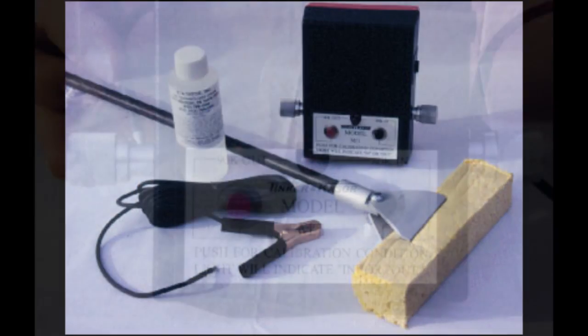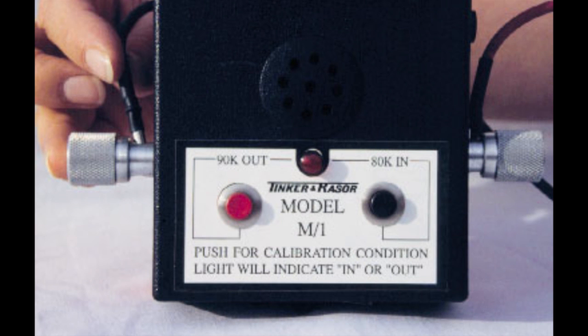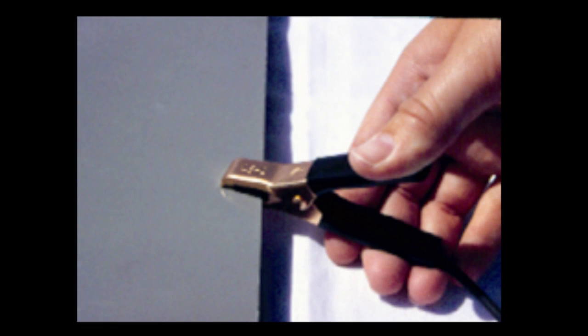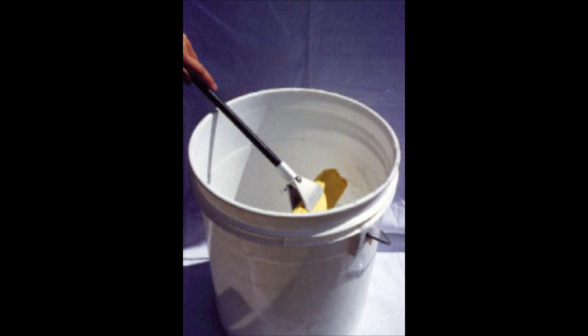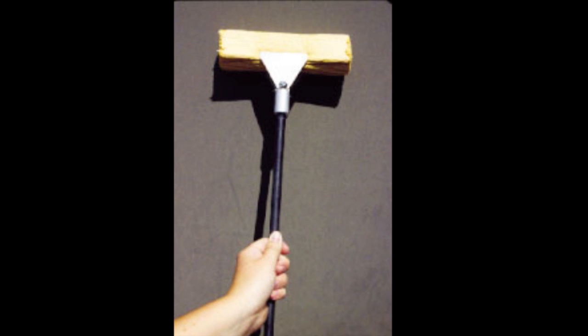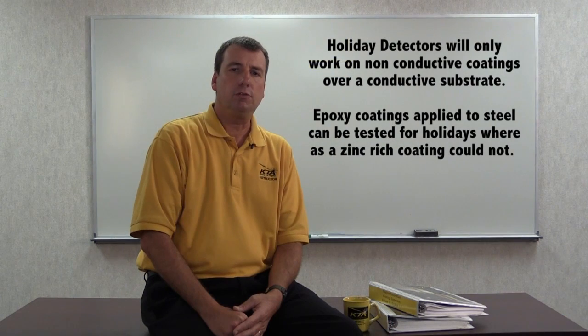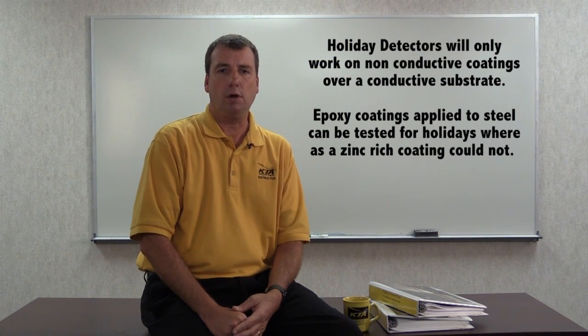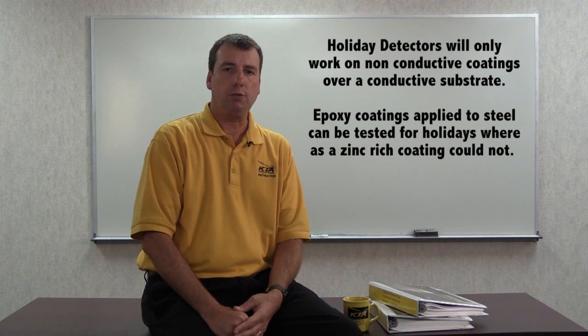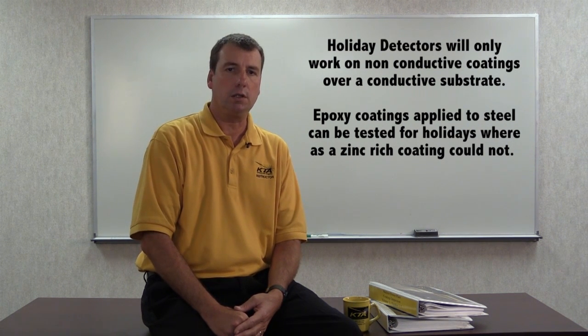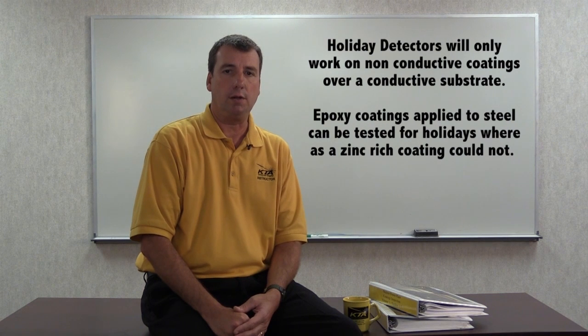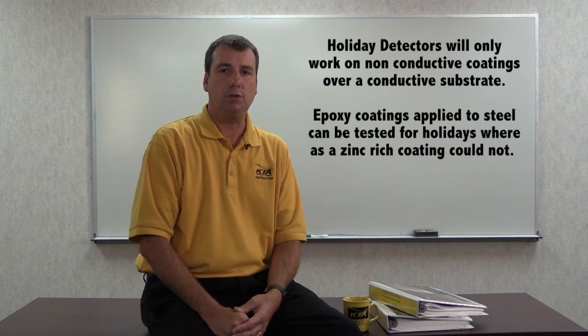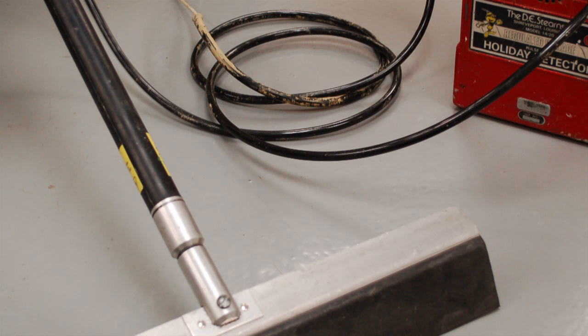Holiday detectors operate by applying a current to the surface of a non-conductive coating and grounding to the substrate. The current passes through the pinholes or misses, completing an electrical circuit, designating the presence of a flaw. Since these detectors will only work on non-conductive coatings applied to a conductive substrate, epoxy coatings applied to steel can be tested for holidays, whereas a zinc-rich coating applied to the same steel could not, since zinc is a conductive metal in the coating. Some high-voltage detectors can also be used to test non-conductive coatings applied to concrete, provided the concrete has sufficient residual moisture to make it conductive.